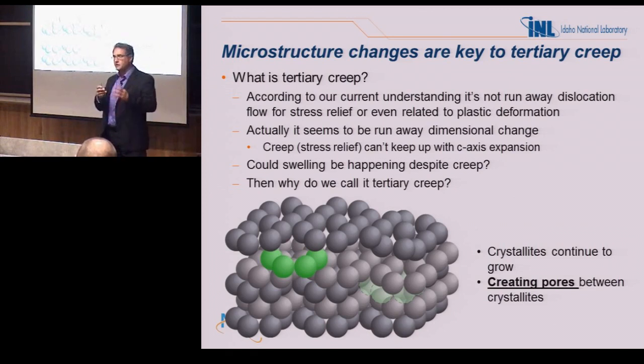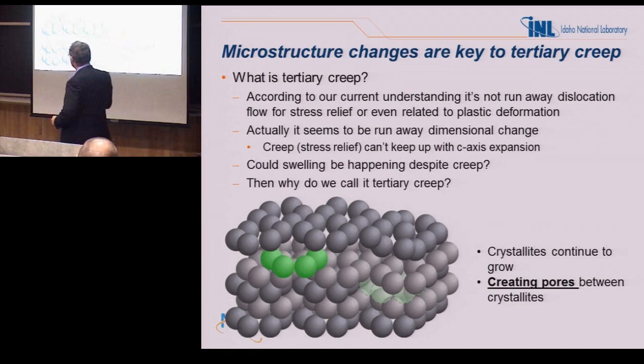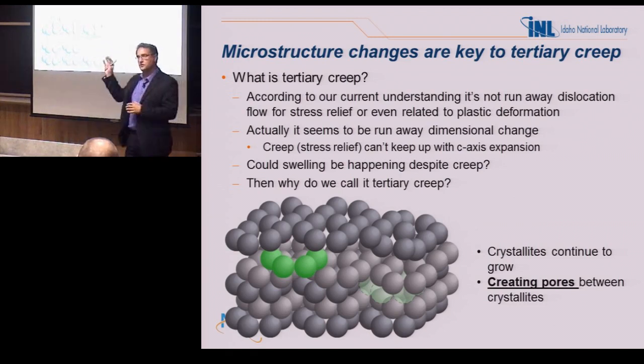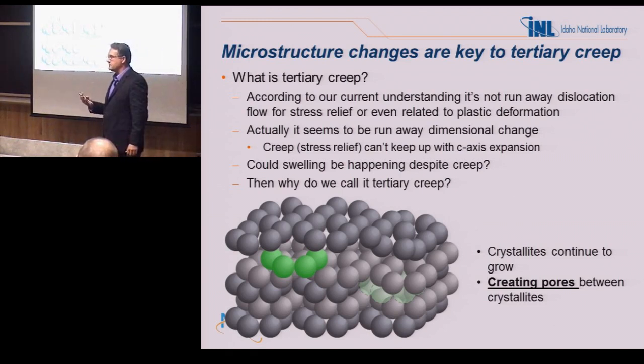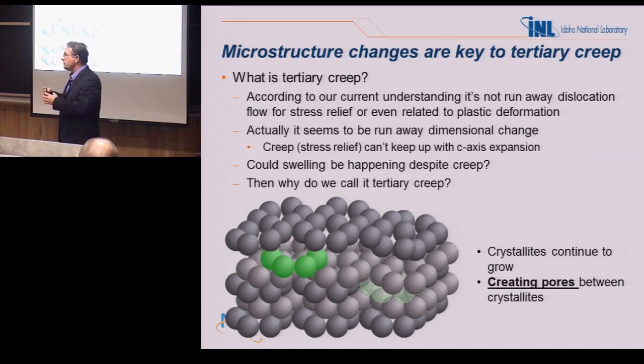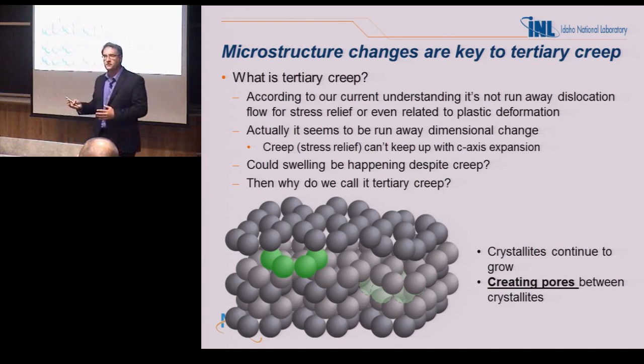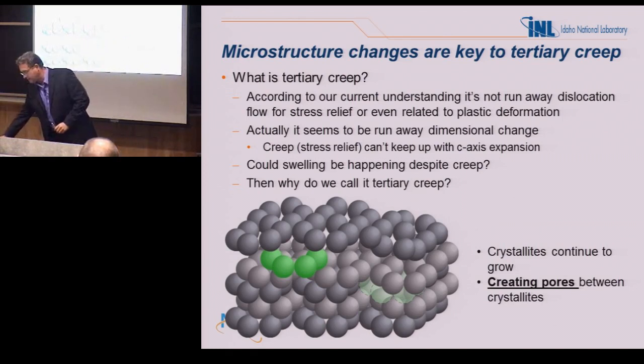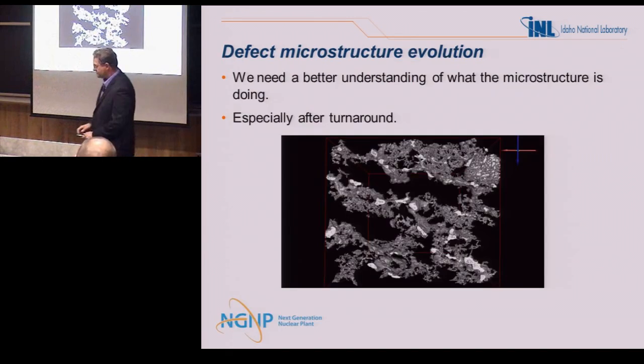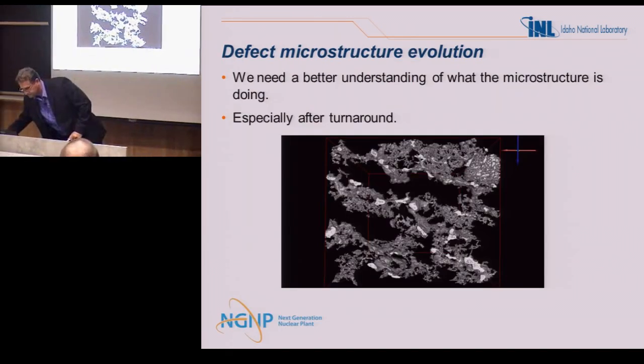Okay? It can go in there and strain a little bit, but as soon as those Mrozowski cracks close, then the C-axis takes off and we cannot keep pace with it with the radiation creep. So that's what you're actually seeing on that tertiary creep. It's a different mechanism. We talk about dislocation flow for primary and secondary, but in the tertiary, it's a completely different mechanism. It's porosity.